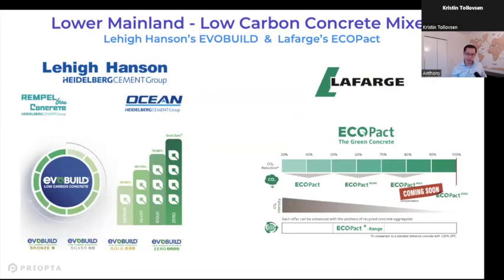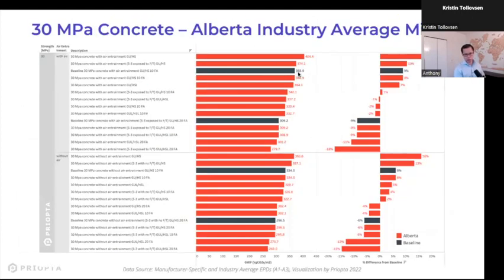However, there have been developments within some of the major ready-mix concrete suppliers in developing their low carbon concrete mixes. For example, Lafarge and Lehigh Hanson, two of the biggest concrete producers, both have their own lines of concrete. Lafarge has EcoPact, with different tiers: regular EcoPact, EcoPact Prime, and EcoPact Max. Similarly, Lehigh Hanson has EvoBuild Bronze, Silver, and Gold. As you go higher in the tiers, there's a higher percentage reduction in embodied carbon. This is something to inquire about on your projects if you're working with these larger ready-mix suppliers, or even the smaller ones. They should be able to generate EPDs for your individual projects, so you can get a good sense of how these compare with, for example, the industry average values, which are these black bars.